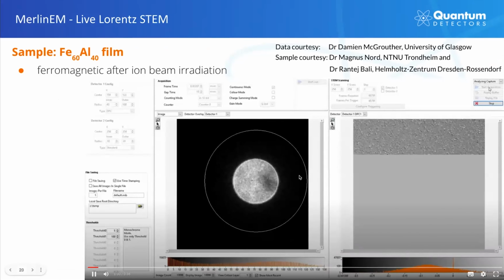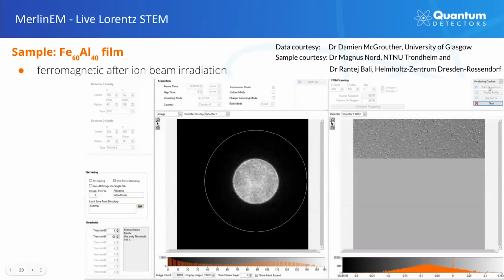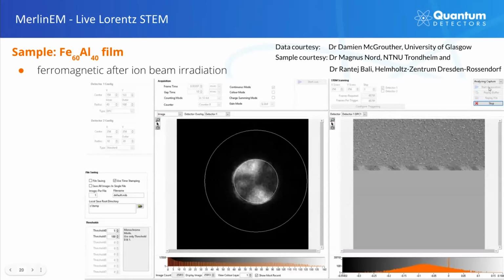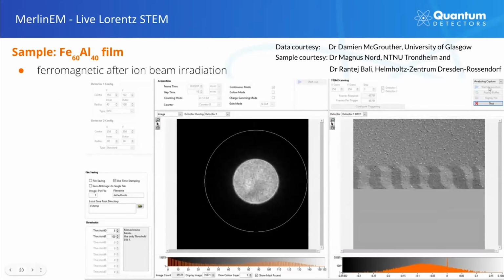Let's now demonstrate the use of MerlinEM software with live imaging. This video will show an example of DPC STEM imaging of magnetic material. So let's play it. The sample is a polycrystalline iron aluminium film, which becomes ferromagnetic after it's exposed to the ion beam. In the live analysis view, we can see the dark and bright contrast appearing, which shows the orientation of the in-plane magnetic field within the sample.